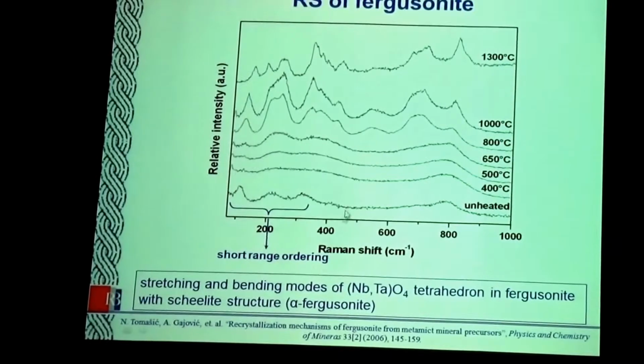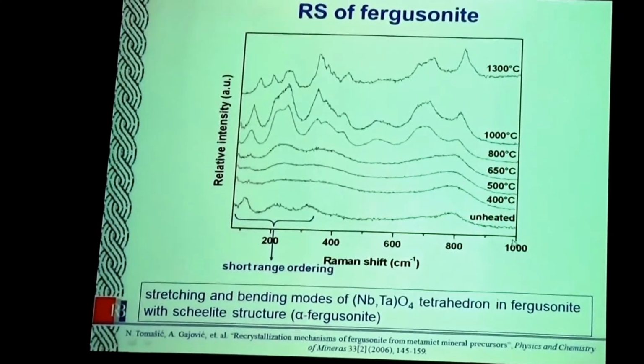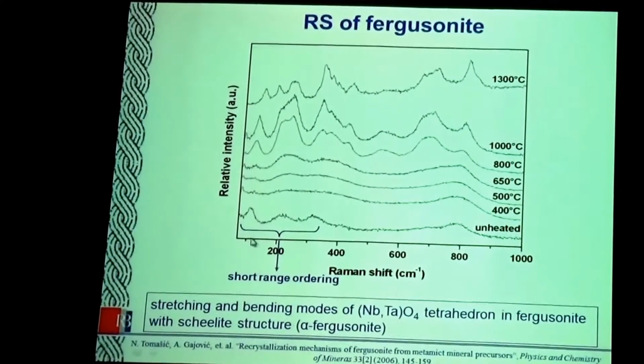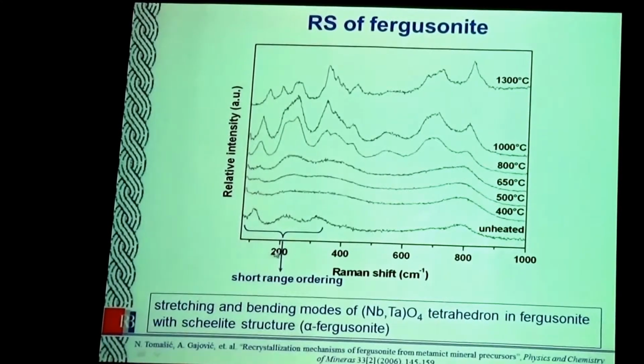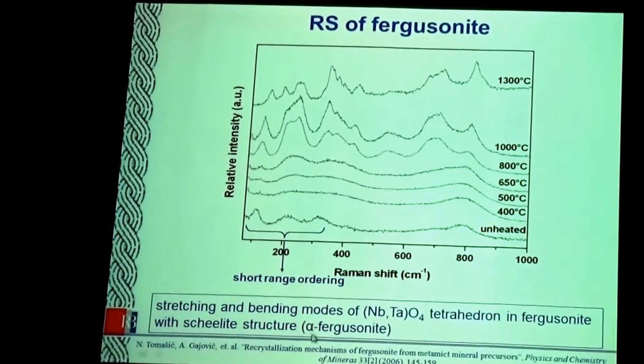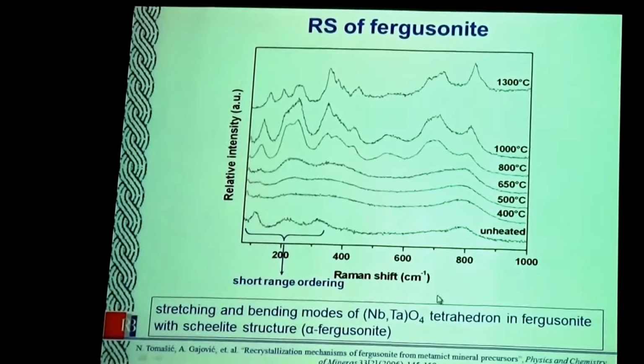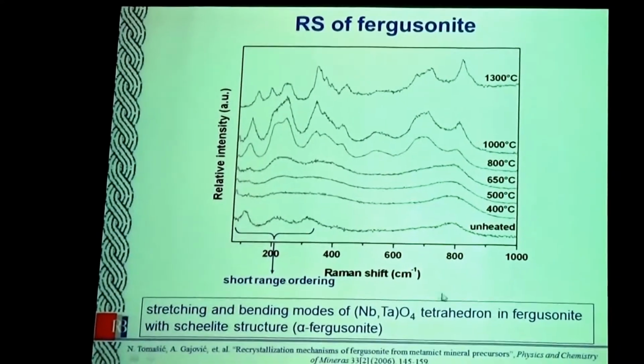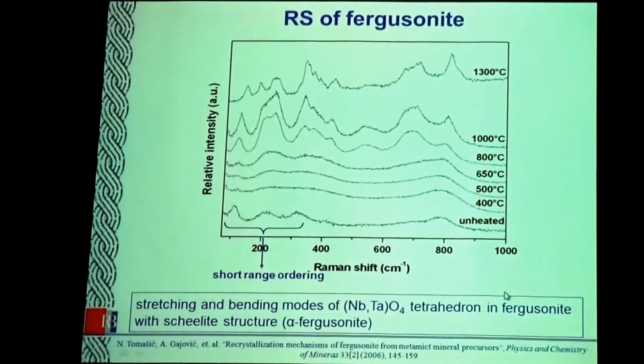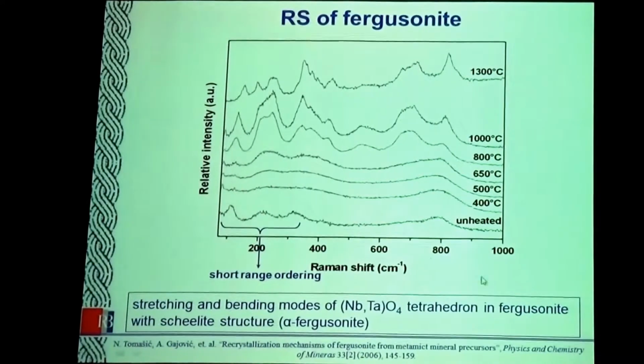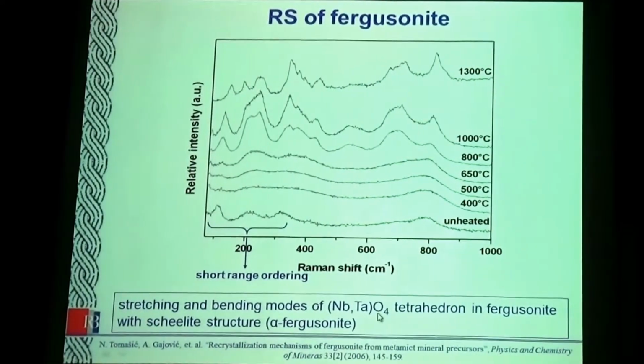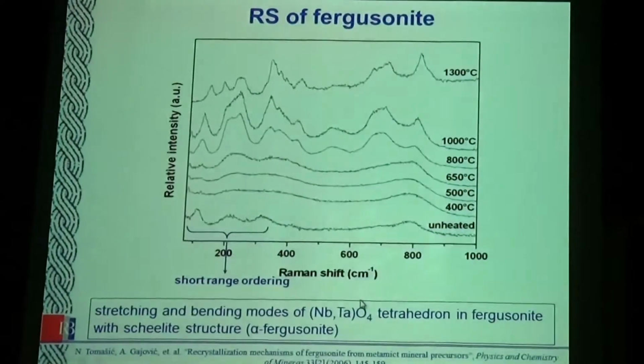We tried Raman spectroscopy, and in the unheated sample we already observed some short range ordering. The position of this band belonged to niobium tantalum oxide tetrahedron vibration, so we concluded that it should be alpha fergusonite.